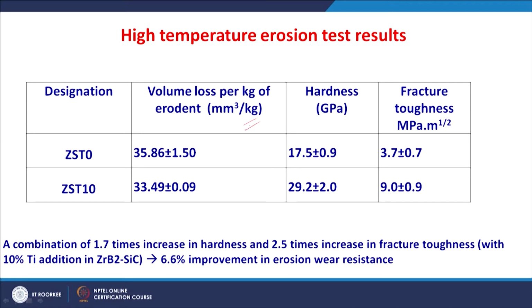So, the high temperature erosion test results show a decrease in the erosion rate from ZST 0 to ZST 10. You can see a change from 35.86 mm cube per kilogram to 33.49 mm cube per kilogram in erosion rate when we add 10% of titanium in the composition.